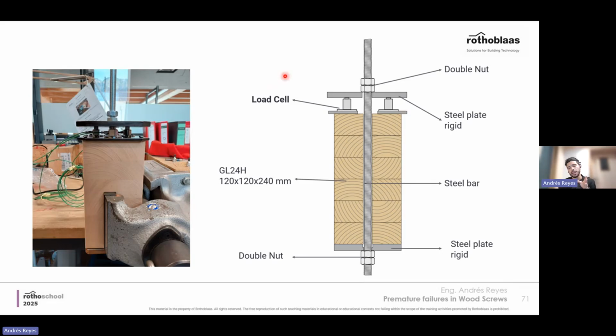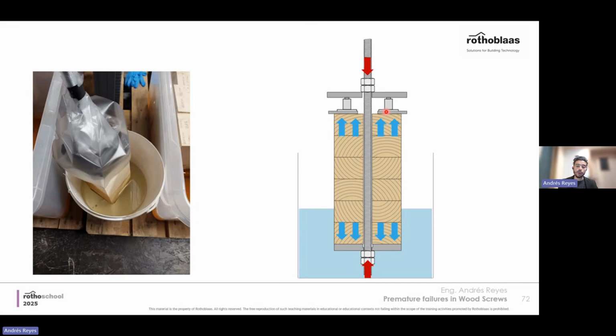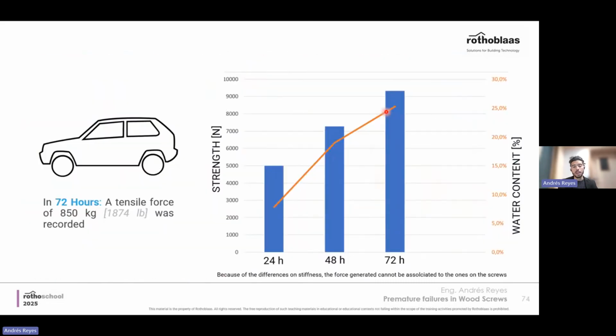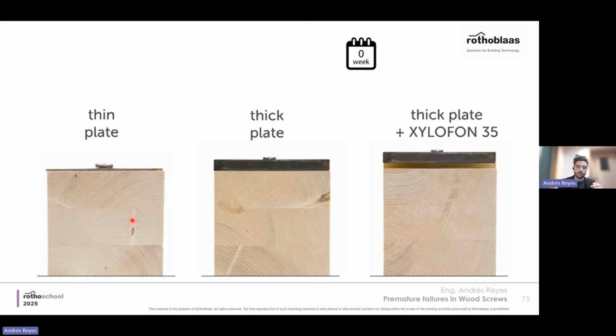If we do this type of testing, adding load cells and putting this type of sample into water, without considering the stiffness added by the screw, in this case we will have more or less 800 kilograms, which is almost 2,000 pounds of tensile force, which is relevant. Not that big, but nonetheless, it's not zero, so it's important.